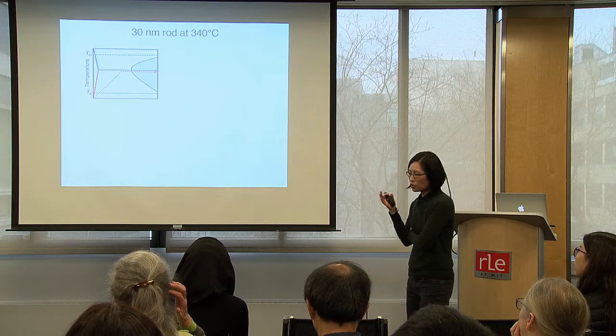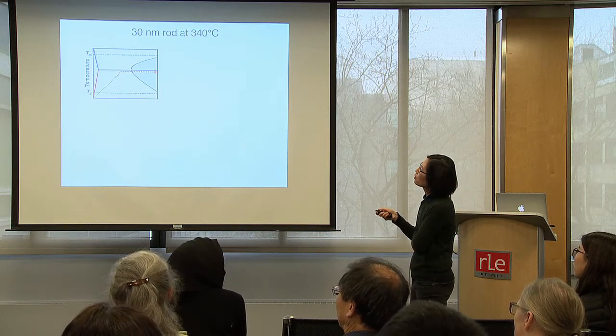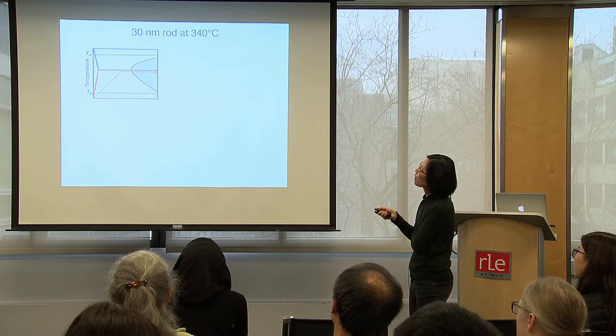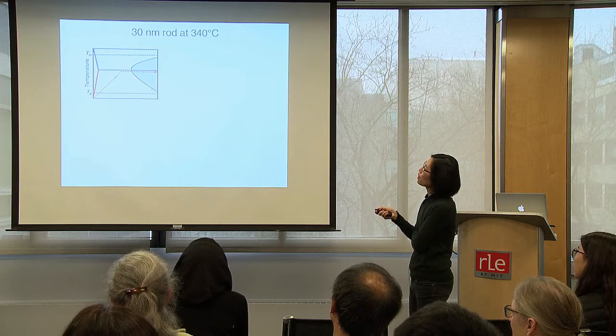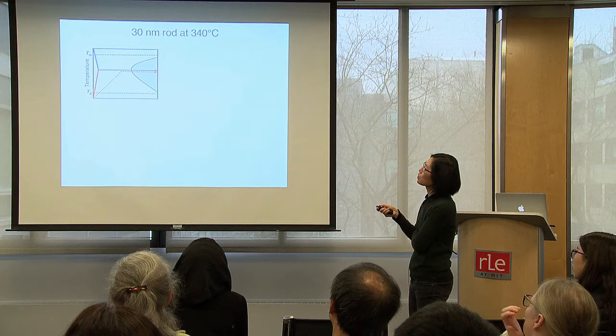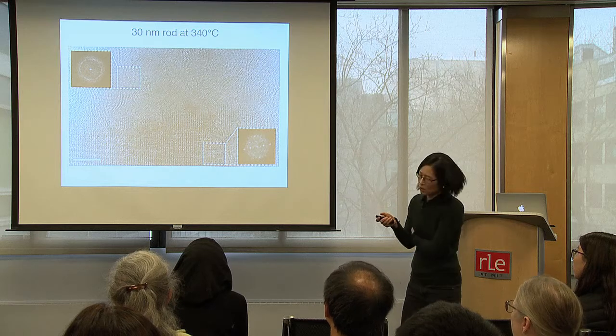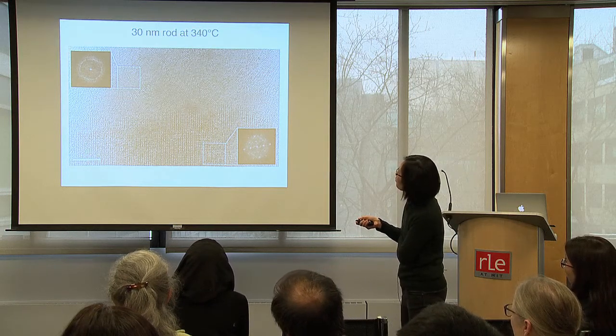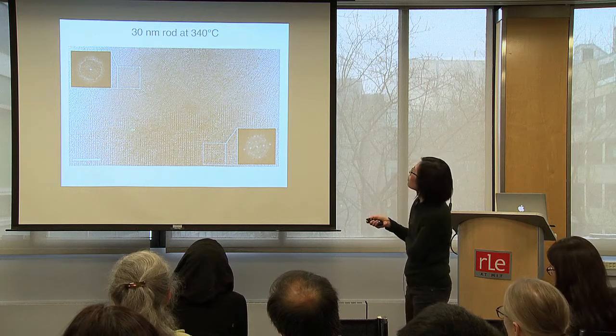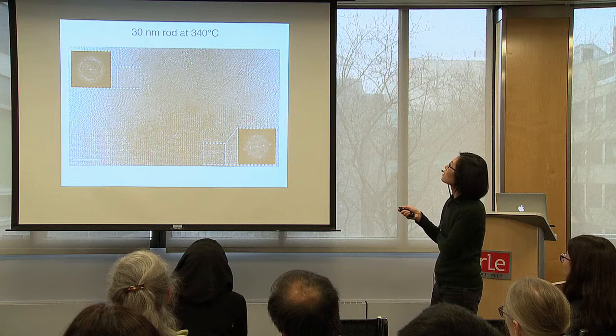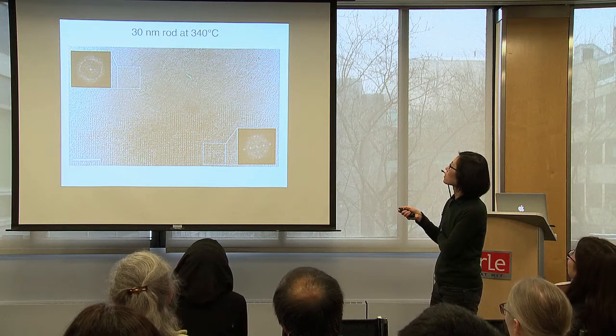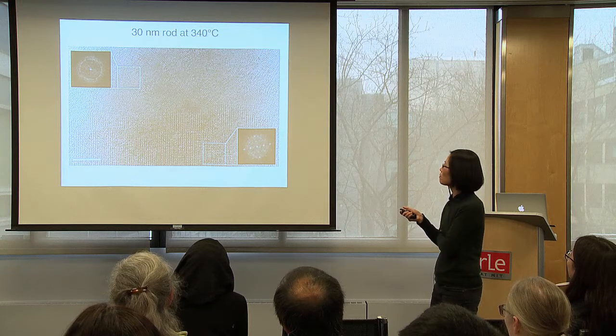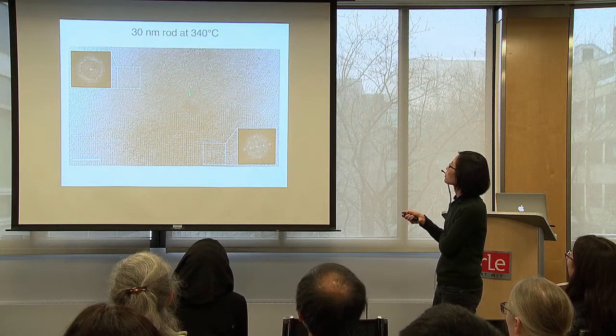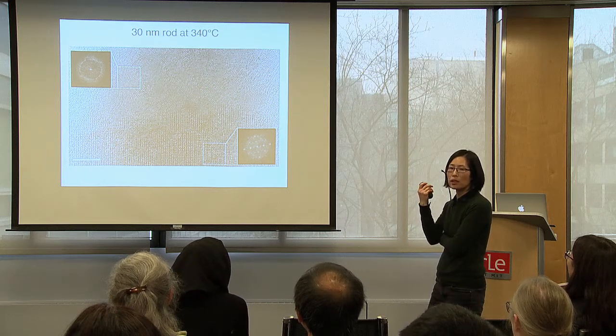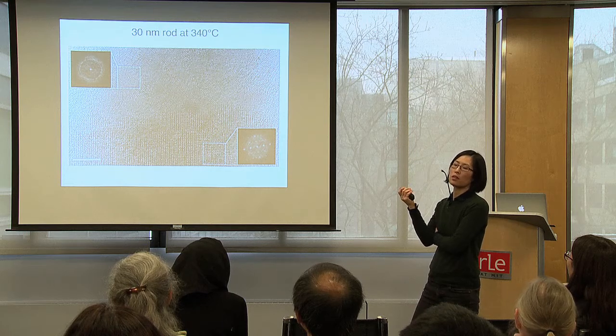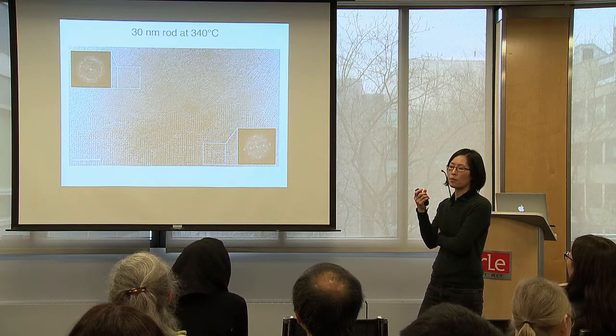So to see if that's really true, we did an experiment where, when we are heating from the glass, instead of going as quickly as possible to our isothermal temperature, we went in with some baking time. And the idea was to create some clusters. This is a little bit of a difficult image. I think the scale bar here is probably 5 nanometers. Here is a single crystalline grain that we have. This is actually glass, but it's not really glass. It's full of small clusters that are arranged. And as this grain is growing, they're quite stable. They may rotate, they may disappear, but the time frame I'm talking about is 2 to 5 seconds. Certainly long enough to really couple to the growth dynamics.